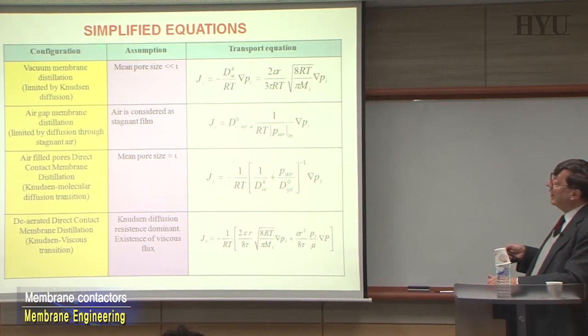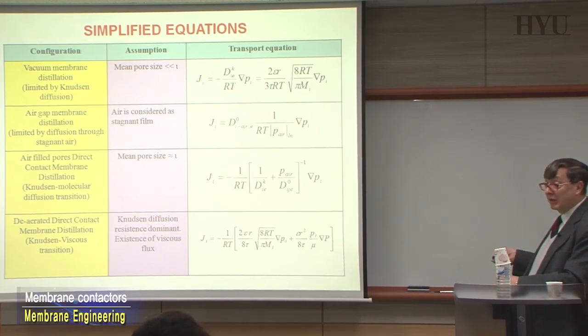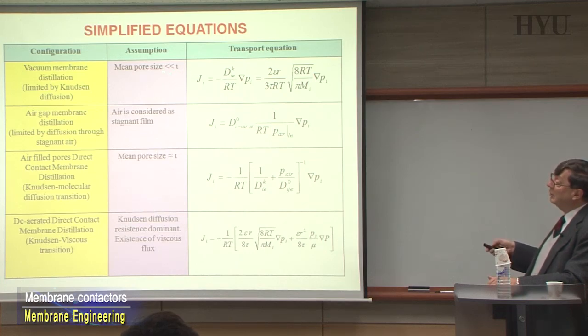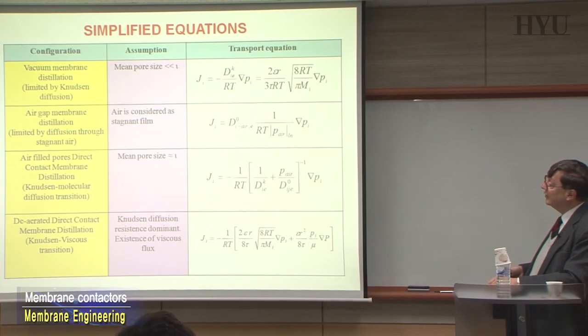And if you now want to utilize this equation, assuming molecular diffusion or Knudsen diffusion for the different kinds of configuration, vacuum, air gap, direct contact membrane distillation, assuming some mean pore size, that means assuming which kind of system it is, you have to take it into consideration. For example, in this case, you are assuming a small pore size lower than this length, where the frequency of collision with the wall, etc., is higher than the frequency between single molecules, the mean free path. And you have here just Knudsen diffusion. Here you can have diffusion through stagnant air. You can have Knudsen diffusion and diffusion transition, and you can have just Knudsen viscous flow. And at the end, each one of these kinds of systems will give you a different relationship, utilizing different equations.